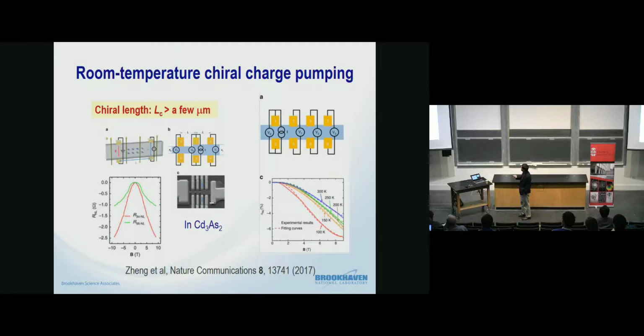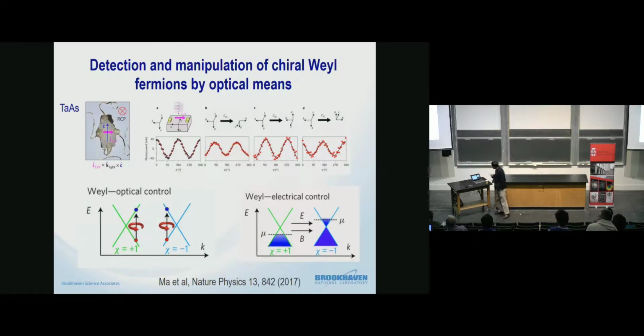And this behavior was also found to happen at temperatures up to 300 K. That's basically a room temperature chiral magnetic effect. They call it chiral charge pumping behaviors over there. So this one is another recent example to show you the detection and manipulation of these chiral Weyl fermions by the optic approach. Now you can also couple these Weyl nodes or the behavior of that with an optic approach. Okay, if you have circularly polarized light shining on tantalum arsenide, this is a Weyl semimetal over there, you can produce a directional current, and this is due to that chiral effect over there.